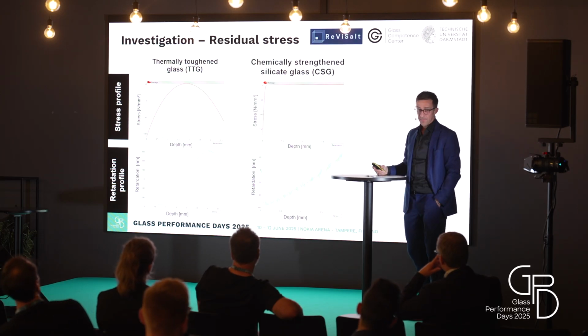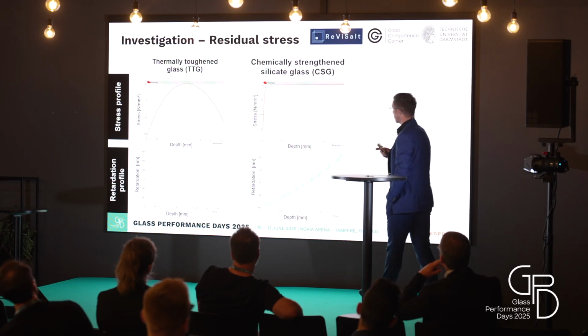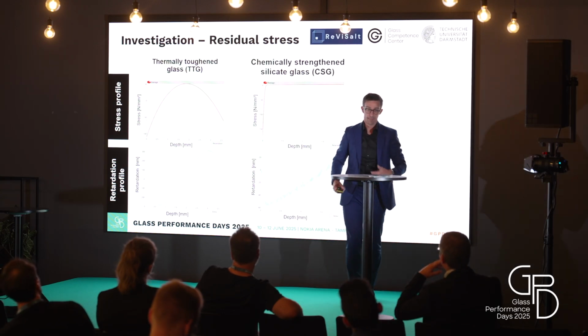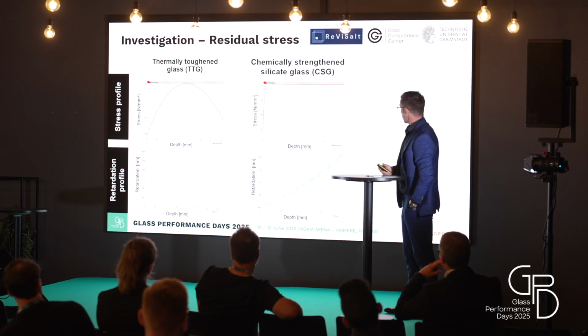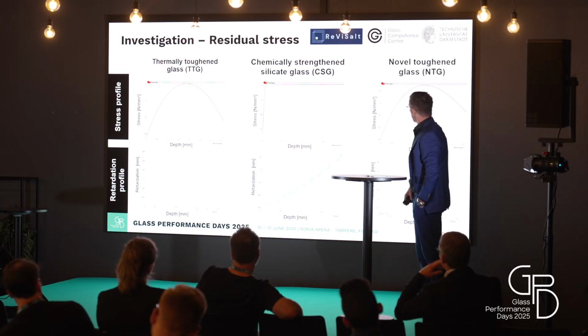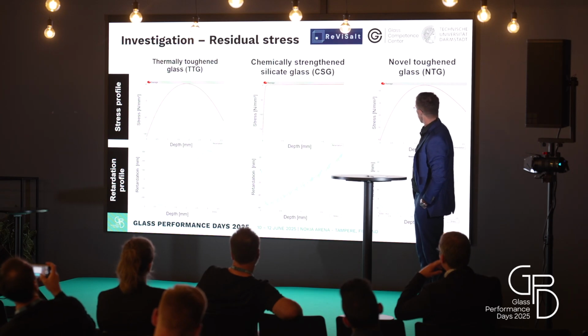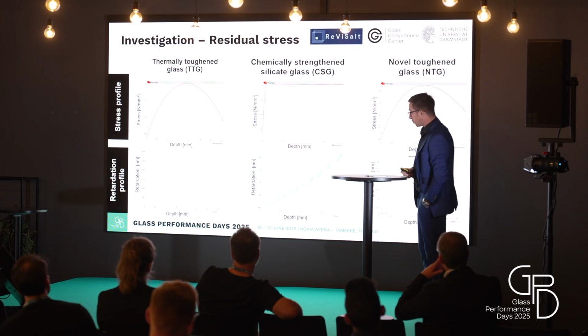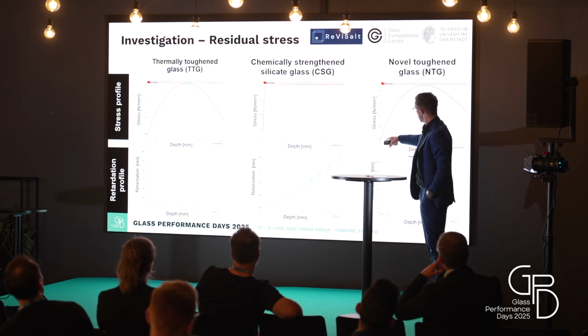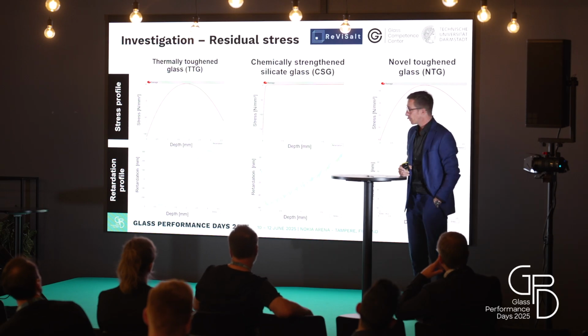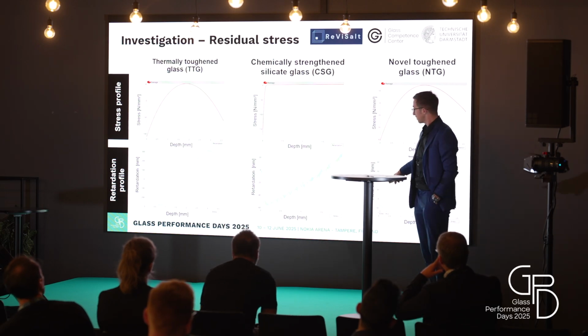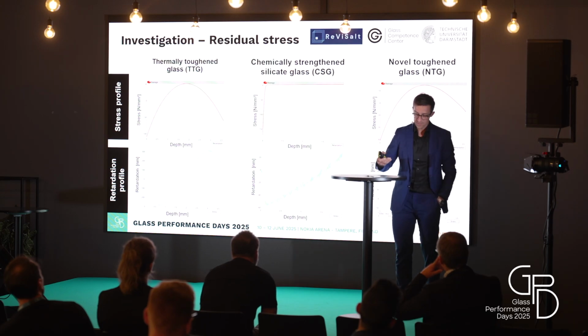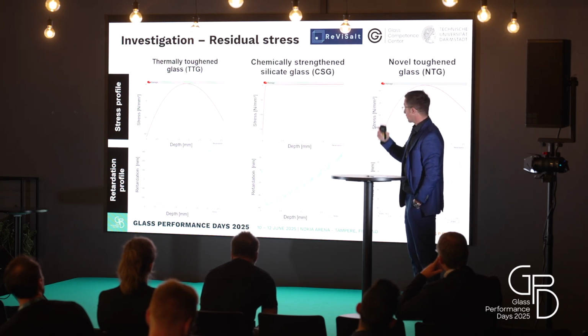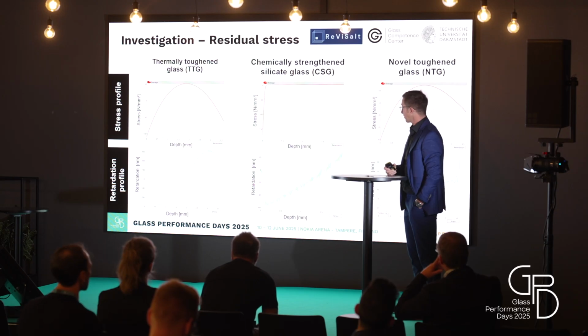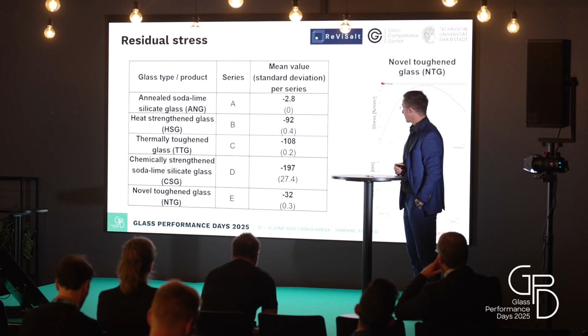This was the measurement for the chemical part. You see also the difference, also here in the depth, some microns. I think this is also typical, also the retardation profile. This was the measurement of the stress profile for the hybrid approach, the novel toughened glass. It was at the moment only possible to measure the thermal part. Here we are in the range of 30 megapascal in compression. This is the retardation curve. It was at the moment not really possible to measure with the SCALP device the stress introduced from the chemical part of the novel process. But I show you some results that it works.